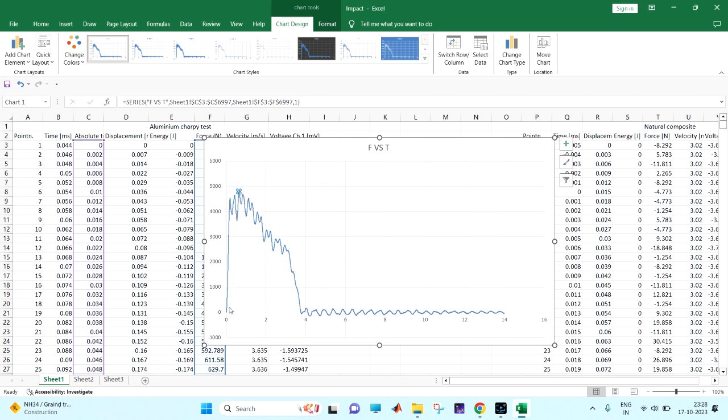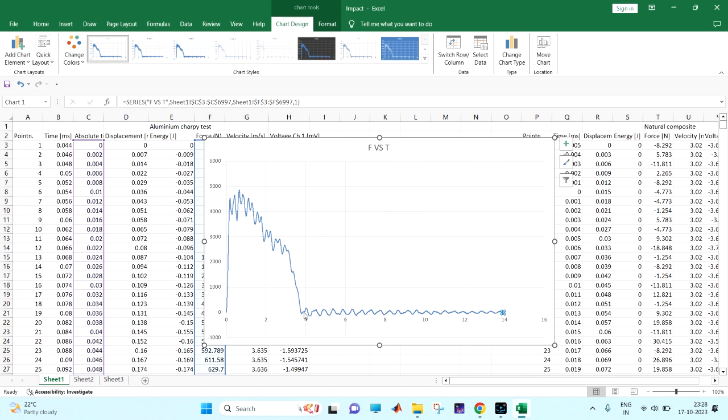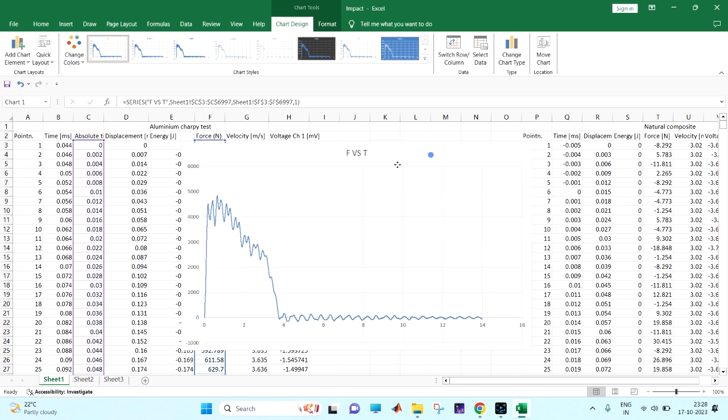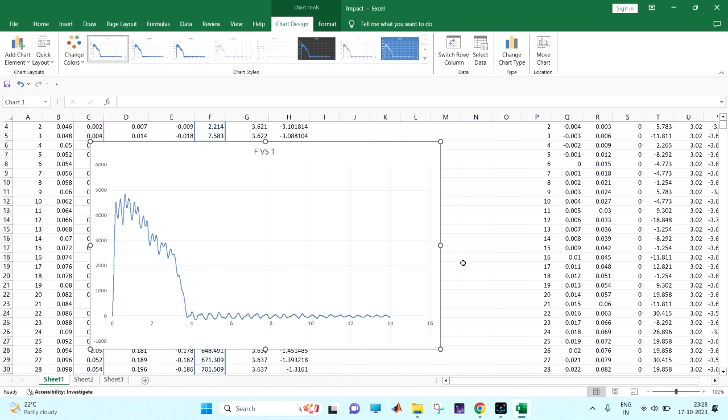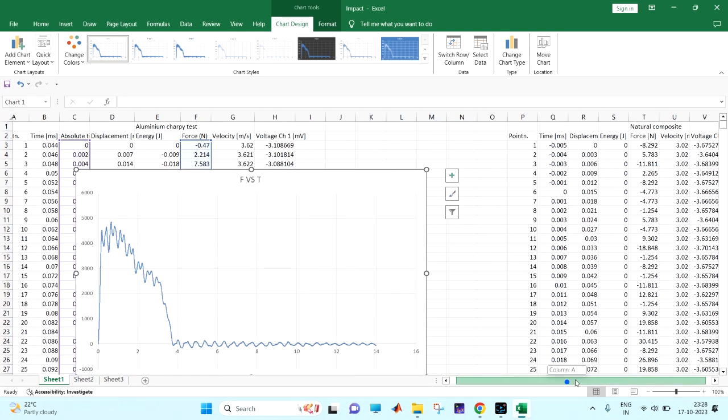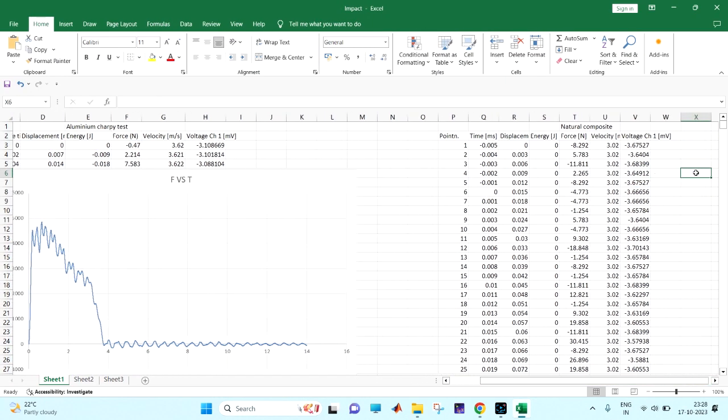It is the maximum force here that is obtained in the impact test of the aluminum. The stiffness is actually the same up to here, and then when we are saying where the first damage is initiated, the stiffness gets changed. There is no meaning of data from here to here, because at this position the force is not changing, only the time is changing. There is no contact forces there. This is the data when this impactor top is moved from the specimen to the home position. So you can go and read these things. I am not interested, I am interested with the natural composites.